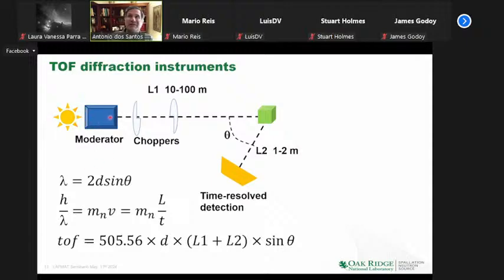Now, because it's literally neutrons flying over a beamline that is multiple meters long, you can define their speeds by choppers. These are mechanical disks with apertures that are spinning at the same frequency as the source, and that limits which wavelength you see. Then you measure the time of arrival on your detector, and you know the angle of scattering. So if you have the wavelength, because you have the velocity, and you have the angle of scattering, then you can do a powder pattern based on the d-spacing of the material. The function is simple enough, and you can do it because the velocities are quite classical. We're talking about milliseconds to microseconds, depending on the length of the beamline.